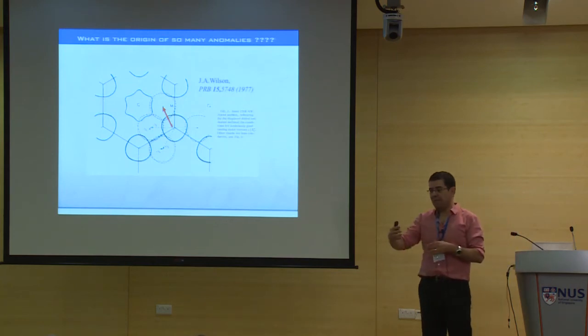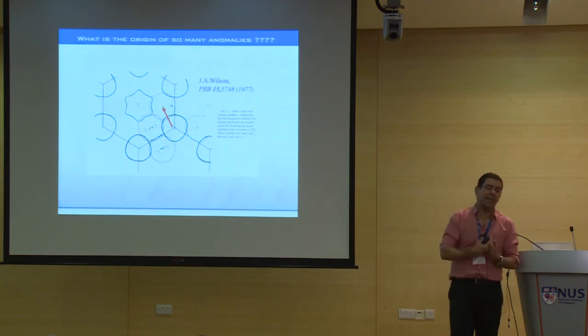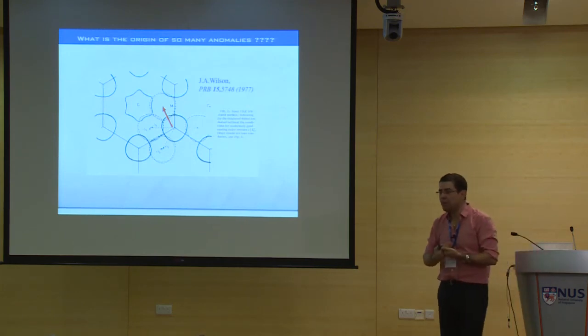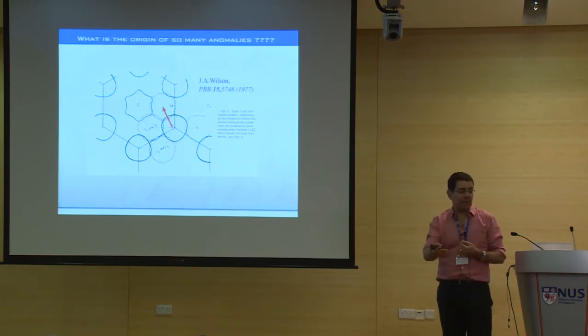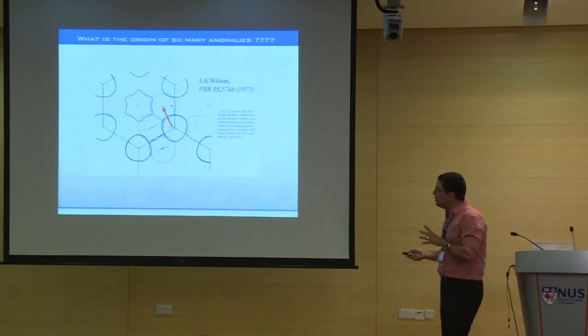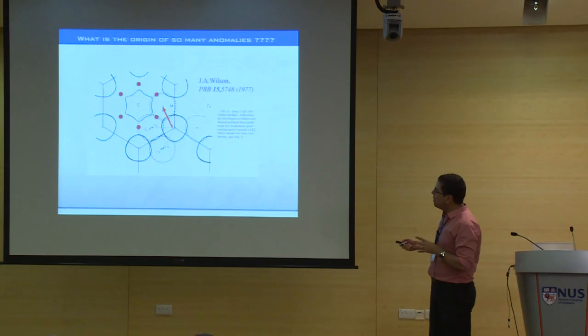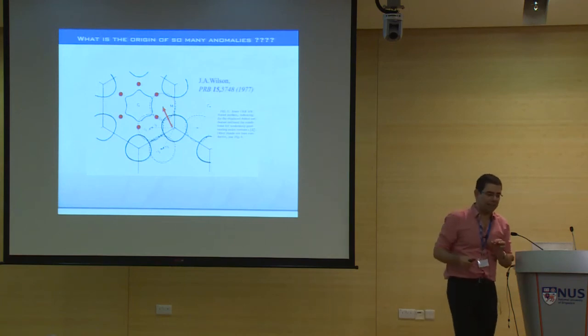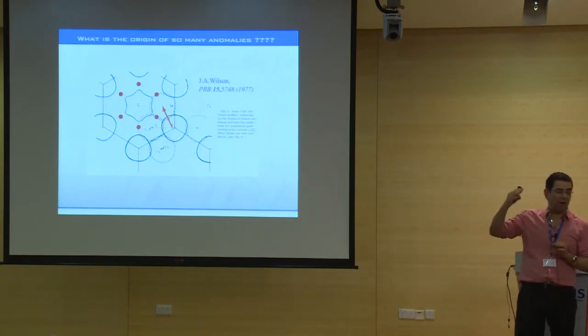When you have two Fermi surfaces that nest well in momentum space, the susceptibility for charge density wave diverges. And that can trigger this charge density wave transition. But at the same time, during more or less the same time, people realized that also very close to the Fermi energy, there are van Hove singularities, not very far away.